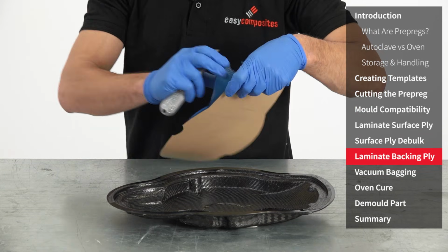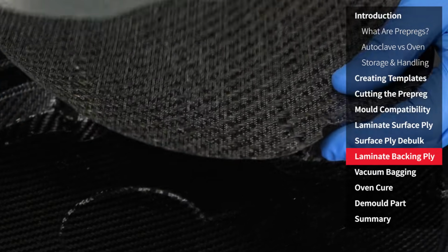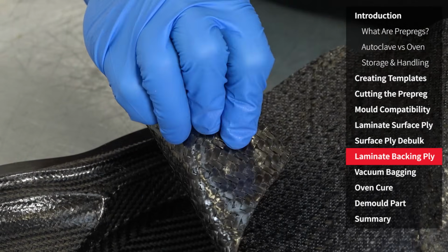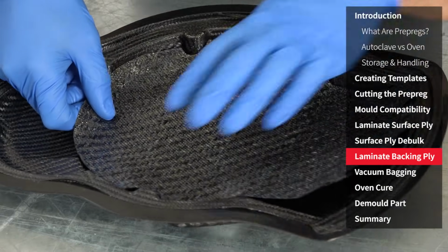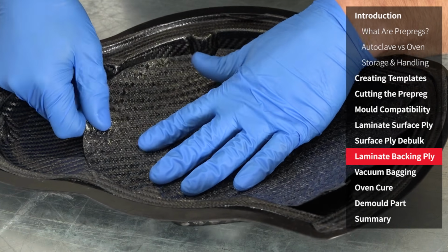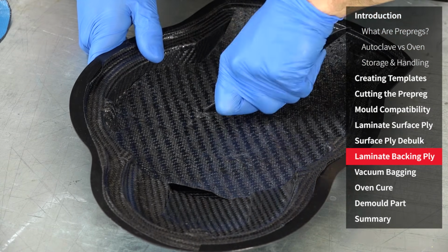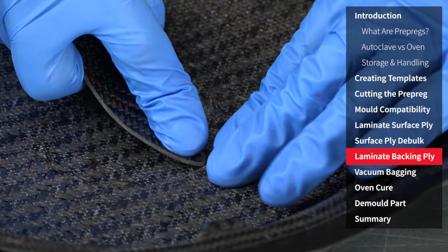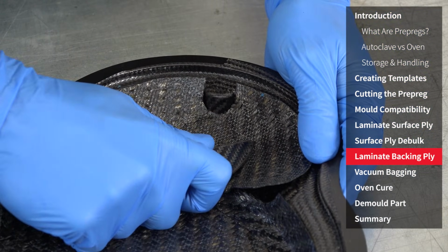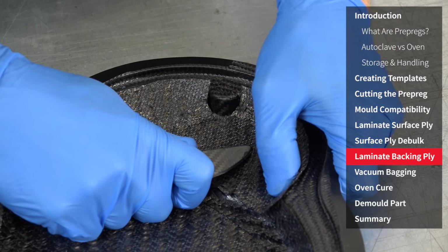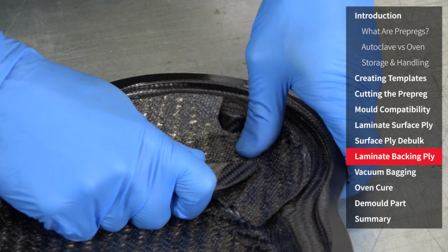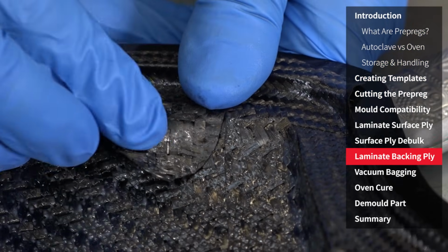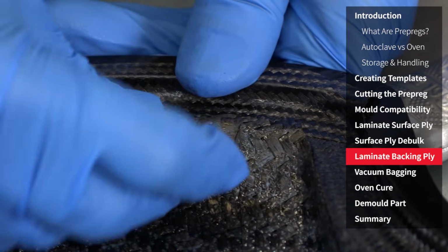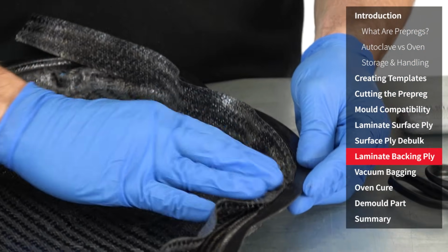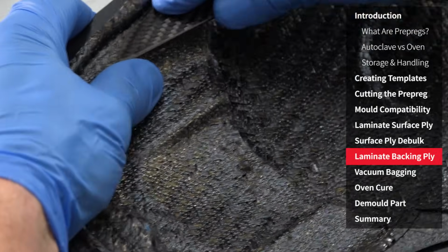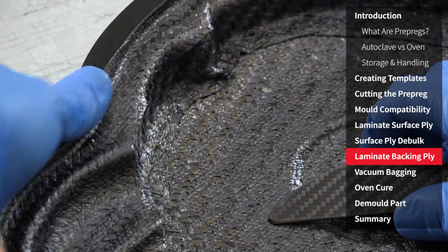We're now moving on to laminating the heavier 450 gram backing ply. As this material is much thicker than the 215 gram surface, it is slightly more difficult to laminate as it doesn't conform quite as easily. But in all other respects, the process is exactly a repeat of the surface ply laminating procedure, and so the same care should be taken to press the material into all of the sharp features and details. Although I'm not using one for this job, in certain circumstances a hairdryer or a low temperature heat gun can help soften the resin, which helps with drapeability. If used, this should be done sparingly so as not to overheat the material.